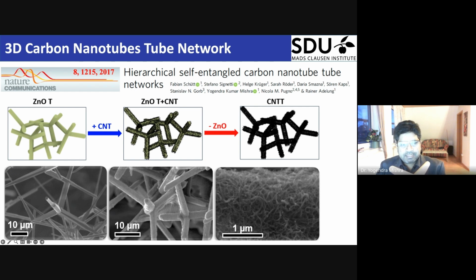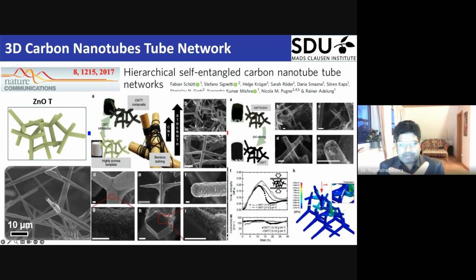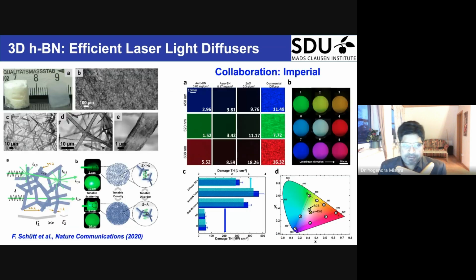Here you see that after adding CNTs onto zinc oxide, they wrap around, and then after removing the zinc oxide, we have a carbon nanotube network. These carbon nanotubes wrap around the arms of the tetrapods like the bamboo lacing we make in our daily life, and they provide huge mechanical strength depending upon the carbon nanotube content. Afterwards, when we have enough content and whole coverage, we remove the template, and we have a nice mechanical strength, very high porosity, several orders of porosity, and nice electrical conductivity. These networks have shown many applications as high sulfur loading cathodes in battery materials or medical catheters. That we have demonstrated.